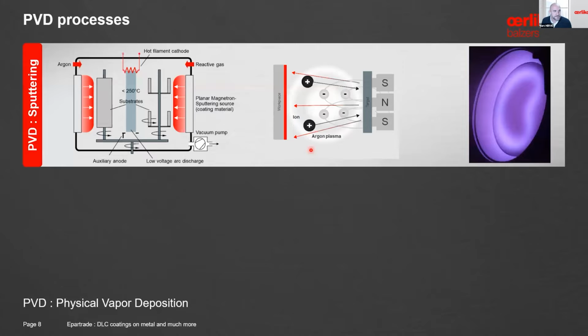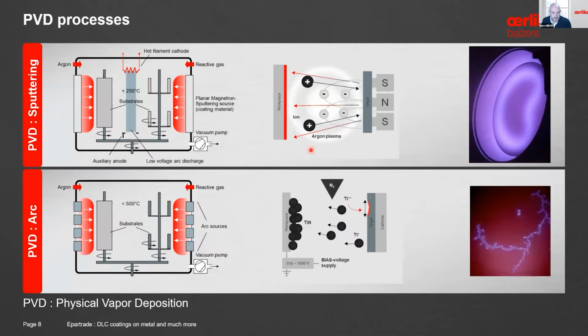When we talk about coating, many people are thinking about paint. It is very often the idea. Our coatings are made under vacuum inside a chamber, and we have different processes to apply the coating. We have the PVD coating, which stands for physical vapor deposition, meaning that we have a physical target of the material that we want to evaporate and the coating we want to make. So if we want to make, for example, a chromium nitride coating, we will use a physical target of chromium. In this process, under vacuum, all the parts will be in rotation. It will be made at different temperatures depending on the process, but at the end it will give us very high hardness, very dense coating to prevent the wear.